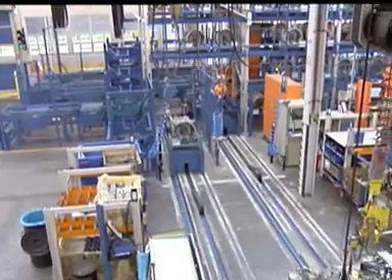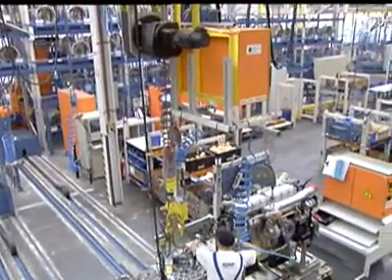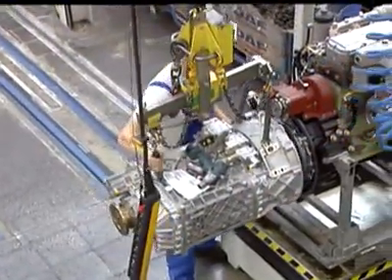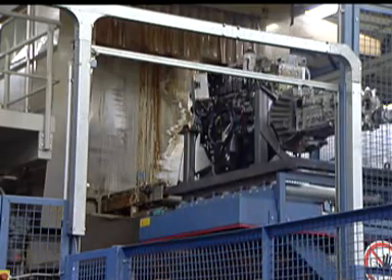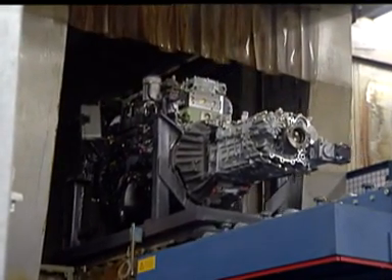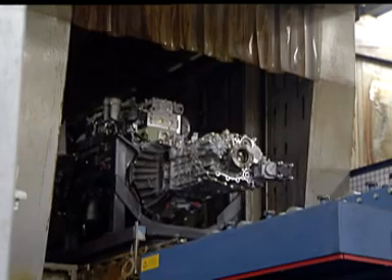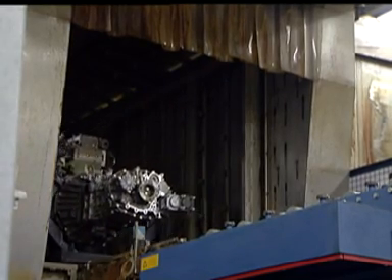At this recently installed trimming line, 12 carriers take the engine along several workstations for mounting the clutch and gearbox and preparing for painting. The engine paint installation, installed in 2000 by EPV of Germany, uses a two-component waterborne grey primer for all engines. By making use of waterborne paint, the emission of volatile organic components has reduced from 2.6 kilograms per engine to only 0.1 kilograms per engine.